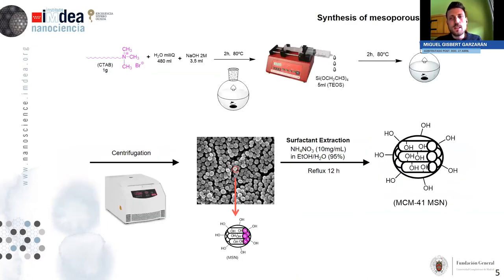Okay, so today I will speak about two types of mesoporous nanoparticles, silica nanoparticles and carbon nanoparticles. So let me introduce very briefly how silica and carbon nanoparticles are synthesized. Basically, for the synthesis of mesoporous silica nanoparticles, we need a surfactant and we need a silica precursor. This surfactant is going to self-assemble into micelles. Then when we add the silica precursor, it will undergo a hydrolysis and condensation around those surfactant micelles. So in the end, we will end up with nanoparticles with that surfactant within the pores.